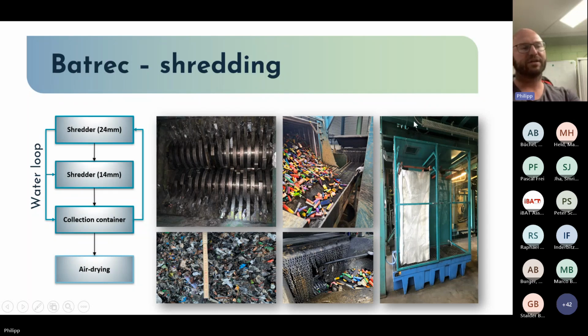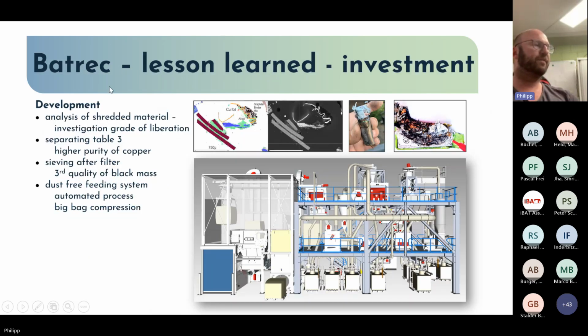After the two shredders, we collect the material in these filter big bags. So after shredding, with splashing water inside, we dissolve the electrolyte in this wastewater, and so our goal is to shred minimum once. So there we are also nearly risk-free, but that we have some good batteries inside this shredded material. So also there the risk of fire is limited for this material. Then we have a drying process by time, and then it's going to our mechanical separation.